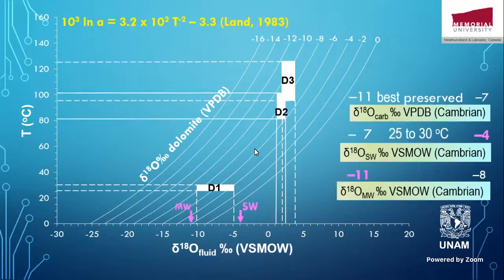Let's look here. We know the temperature of dolomitization from the homogenization temperatures of the cements D2 and D3, and we measured the delta O18 of the dolomite in the lab. We can get an estimate for the parent diagenetic fluids, and we can see values between +1 to +3, and another one +2, +3 to +4. So the compositions are overlapping, suggesting that they were created almost from the same diagenetic fluid, whose isotopic composition just evolved with progressive burial.